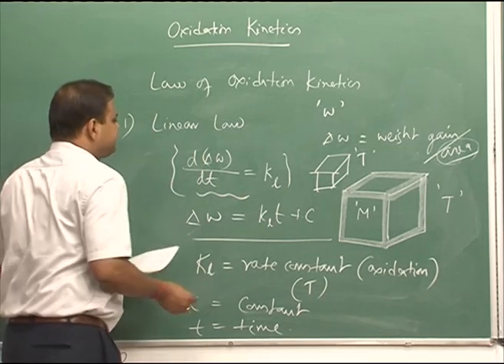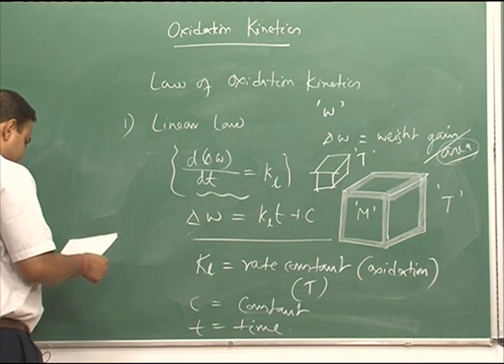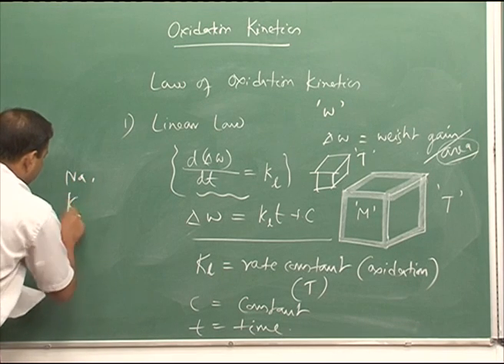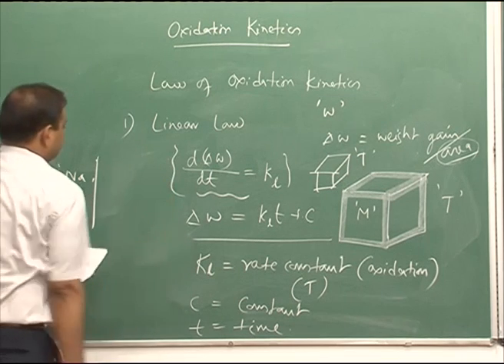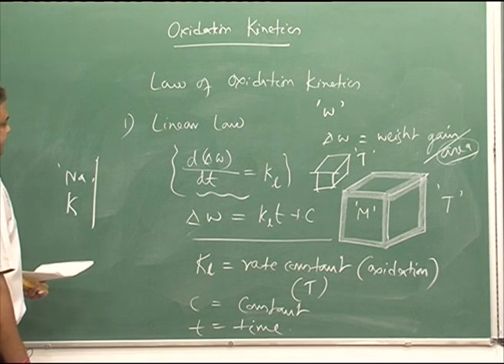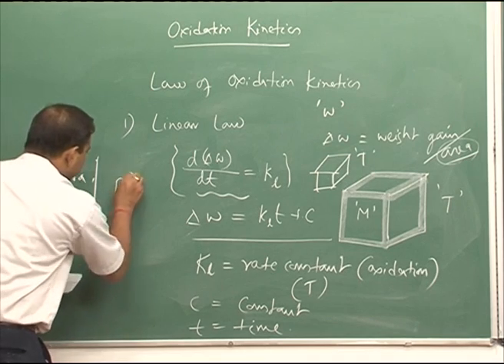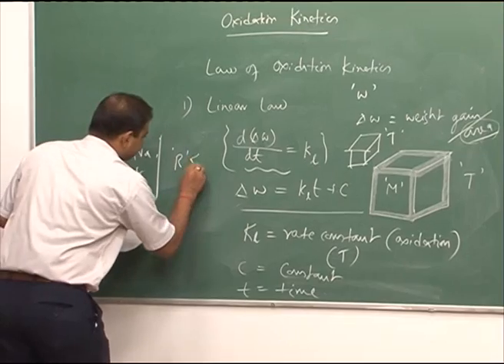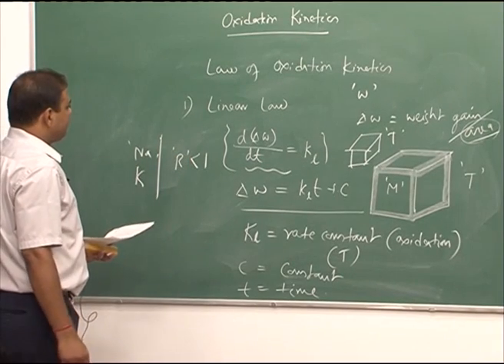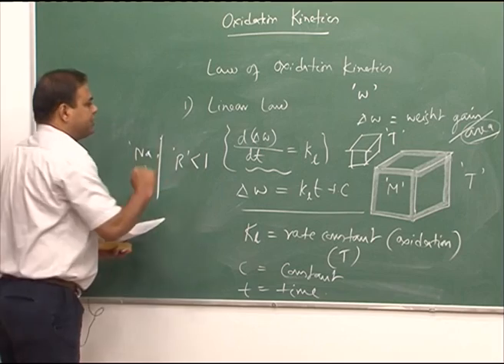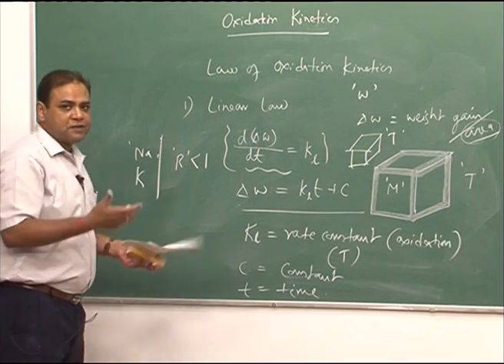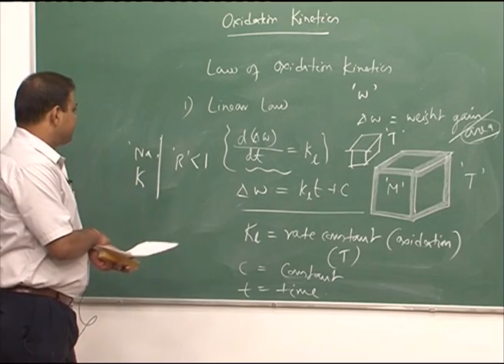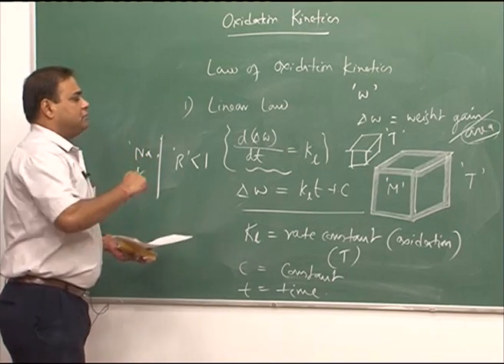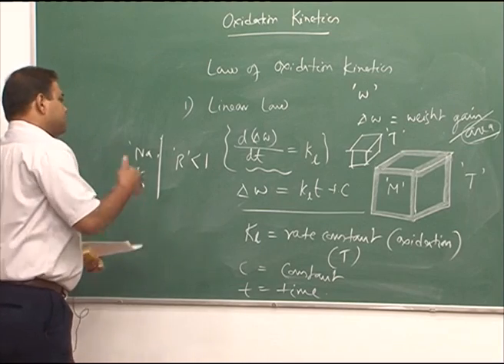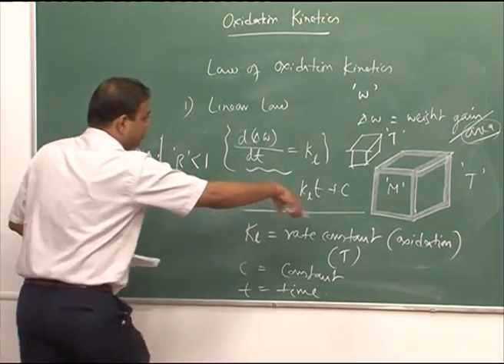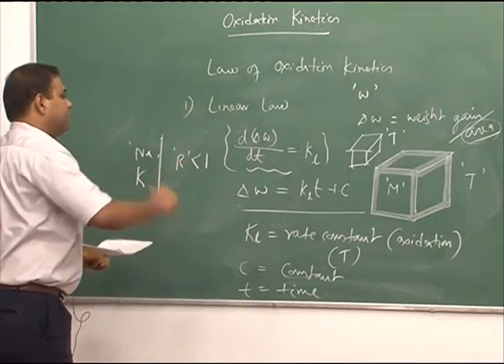For example, this is linear law. The examples of linear law are basically sodium and potassium, where we see that the linear law is followed. In that case we generally see that the R value, which is the Pilling-Bedworth ratio, is less than 1. If R is less than 1, that means the volume of metal oxide is not sufficient to cover up the entire surface. So, the metal surface is exposed to the oxygen all the time, and so the oxygen can oxidize the metal in a linear fashion.